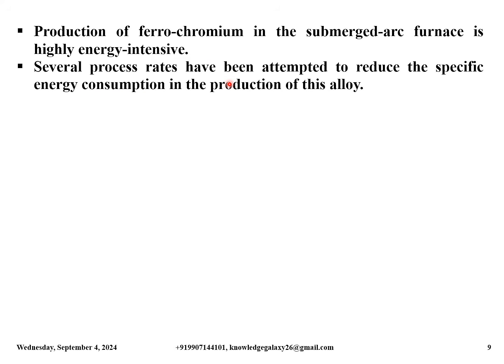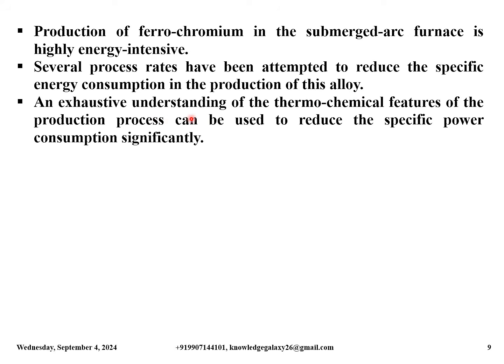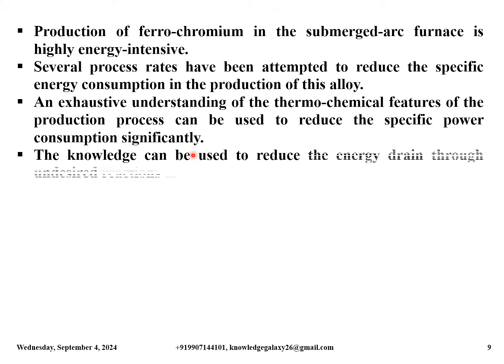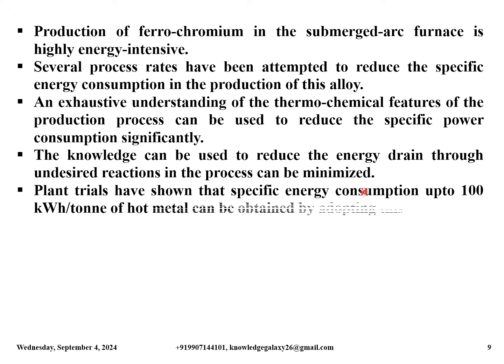Several process ways have been attempted to reduce the specific energy consumption in the production of this alloy. An exhaustive understanding of the thermochemical features of the production process can be used to reduce the specific power consumption significantly. The knowledge can be used so that the energy drain through undesired reactions in the process can be minimized. Plant trials have shown that specific energy consumption up to 100 kWh per ton of hot metal can be saved